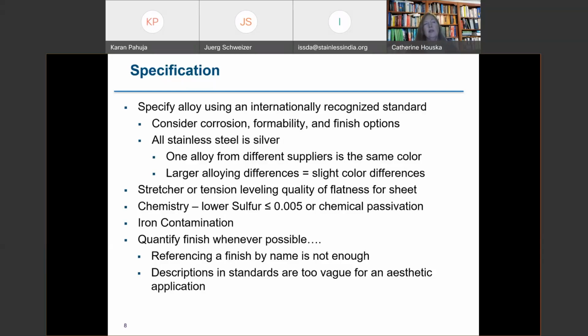For alloy product forms like bar, for example, that can have higher sulfur, it is important to chemically passivate the surface. For sheet and strip and other product forms, specifying low sulfur can help when you have a mirror finish, because otherwise small sulfides in the surface as it's polished to a mirror level can look like little pinholes. So chemistry can make a difference.